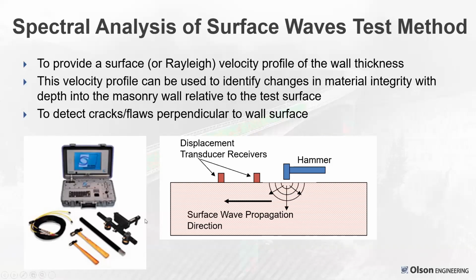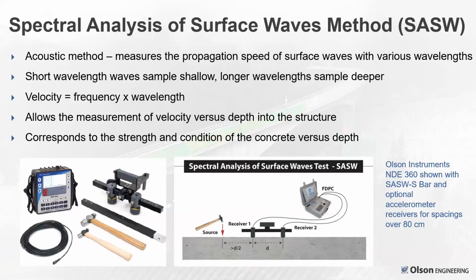So impacting with a small hammer, typically you get higher frequencies, a smaller impactor, and lower frequencies to see deeper with a larger impactor. But in concrete, it often doesn't take too much of a change of that impact source. A small ball peen hammer works for most applications. So what are we doing? Shorter wavelength samples shallow, longer wavelength samples deeper. In velocity, the fundamental physics is velocity is equal to frequency times wavelength. So this corresponds to the strength and condition of the concrete versus depth, because you're measuring the variation of velocity versus depth, technically wavelength, into the structure.